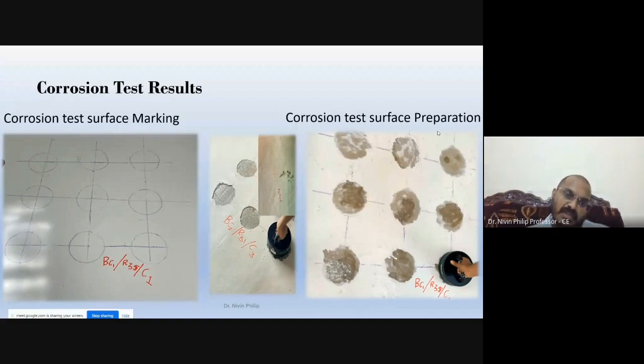Before going to that, the concrete surface should be properly prepared for the equipment. Any painting or anything should be removed before the test, because with an in-between layer, we cannot identify the exact percentage of corrosion. So what we have done is grid this form. In corrosion resistance, we are mapping a whole area, maybe as a contour. How much area can we contour? Maybe 10, 20 or 30 meters, no issues. At least 4 points are required to make a contour.